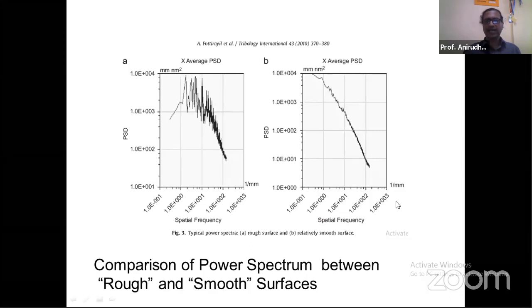So on the x-axis, you will find this frequency. Now, if you see this between the rough and the smooth surfaces, if you find the centroid of this system, that means some mean frequency which belongs to this surface and a mean frequency which belongs to the surface which is smooth. When the surfaces are rough, we saw that the centroidal frequency or the mean frequency associated with this power spectrum moves further towards the right, whereas in this case it moves to the left. So this has got a connection with the frequency of packing of different levels of roughness features on this surface.